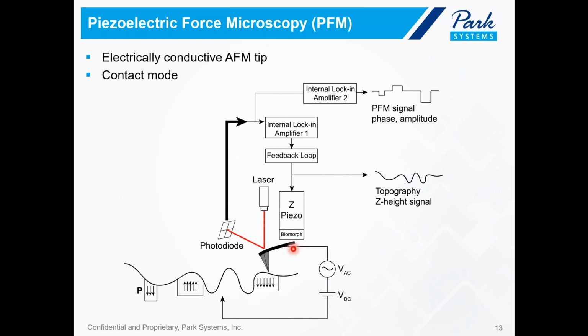And if your material is piezoelectric or ferroelectric, it will respond to this applied AC bias. However, this response has a very low signal-to-noise ratio and must be separated from the topography signal to be able to be read out. So Park achieves this by using a second lock-in amplifier, as you can see here.